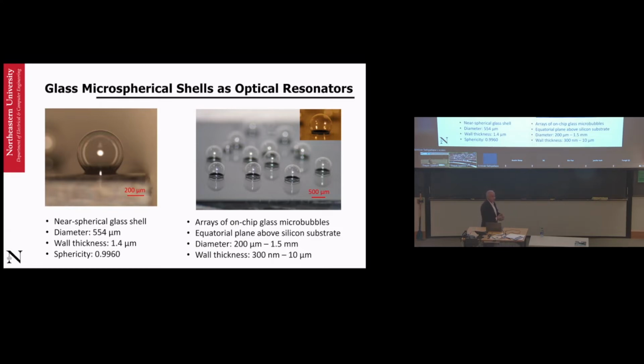We can make complex glass microstructures, but then you need microscopes to see those and admire them, okay? But they're fun. So the nice part was, once we got these very thin shells, we can control their diameters. We can control the shell thickness by playing with how much glass we have, how much silicon we have, or the cavity we have, the pressure. And basically by playing with the process, we can create all these kinds of structures.